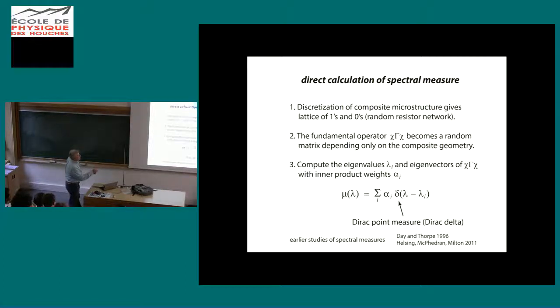And if you discretize, say, an image of a composite microstructure, it gives you a lattice of ones and zeros, a random resistor network. And then this fundamental operator, chi gamma chi or gamma chi, depending on the formulation, becomes a random matrix, which depends only on the composite geometry. So we have a random matrix, and then we can compute its eigenvalues and eigenvectors, and then from those we can actually directly construct this spectral measure.